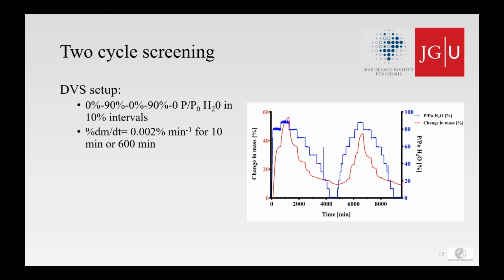So here you see that the first cycle is comparable to the previously shown experiments, including also the incomplete desorption phase. And the second cycle is different. It shows an earlier mass increase and a lower maximal mass. So this clearly indicates that a chemical change took place here. Otherwise, we would observe 2 identical sorption and desorption cycles.